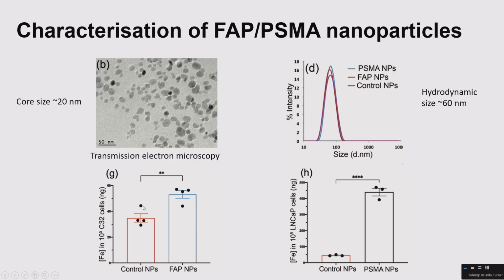So then before we start injecting into preclinical models or things like that, we have to show validity in an in vitro model. So here are some cell binding assays. C32 cells are FAP positive. And so we have control nanoparticles that have no targeting ligand, and our FAP nanoparticles showed a significant increase in these FAP positive cells relative to the control nanoparticles, which is great, that's what we want. And the same sort of thing happened with the PSMA nanoparticles, where we tested these in LNCaP cells, which are a prostate cancer PSMA positive cell line as well. So that was good.